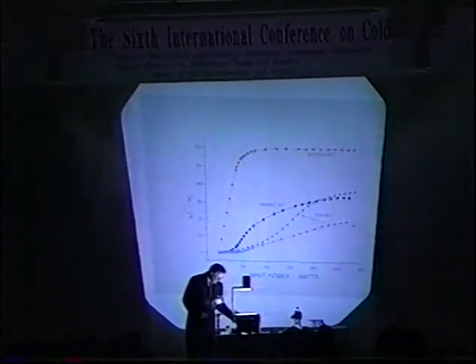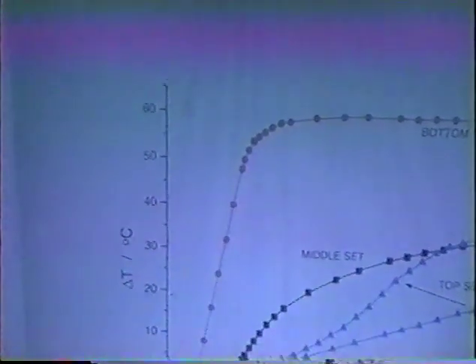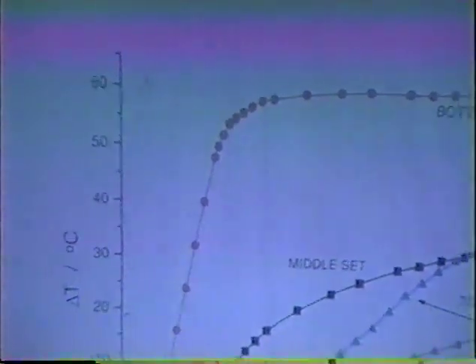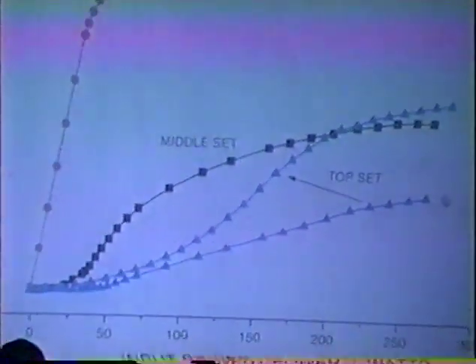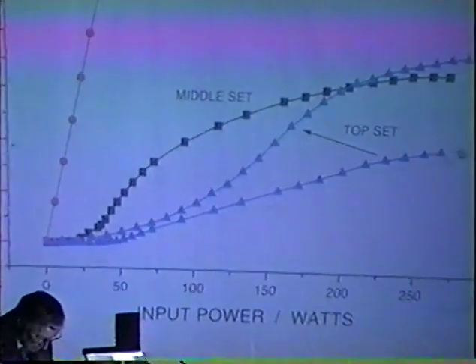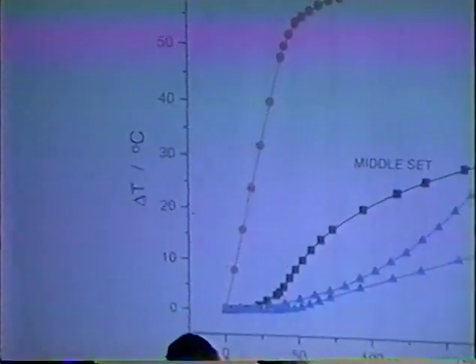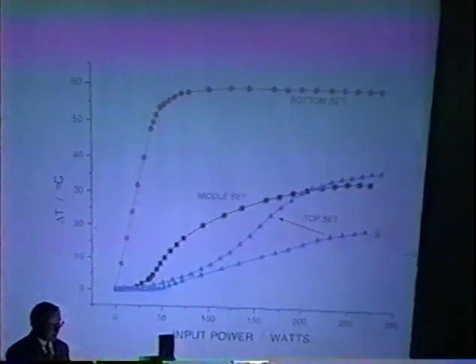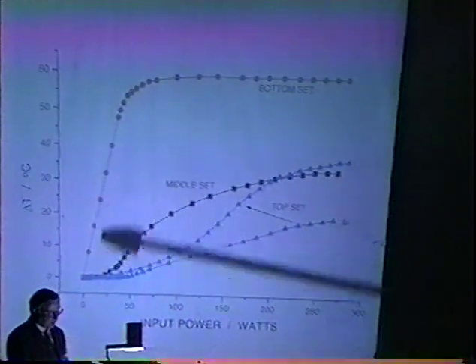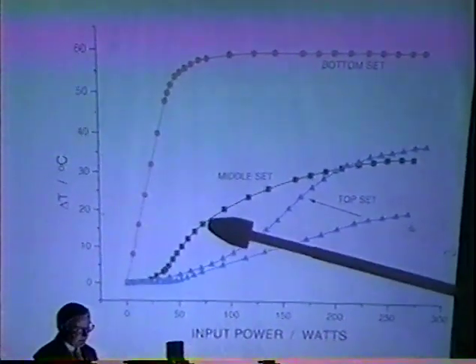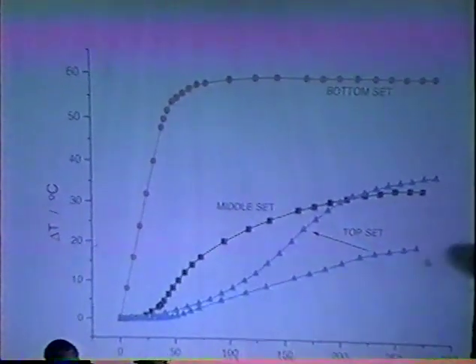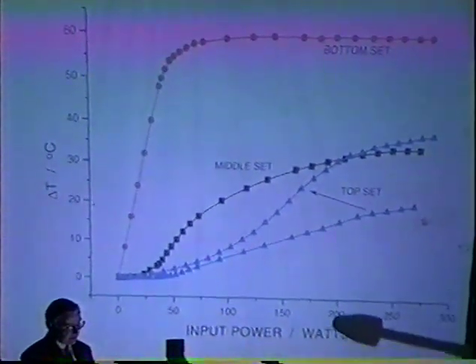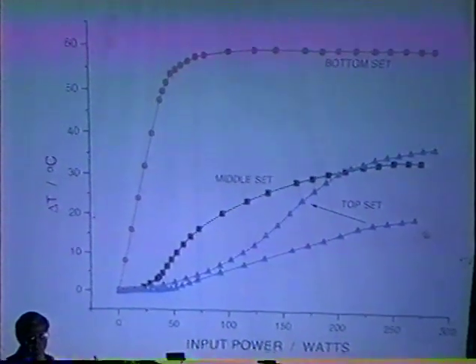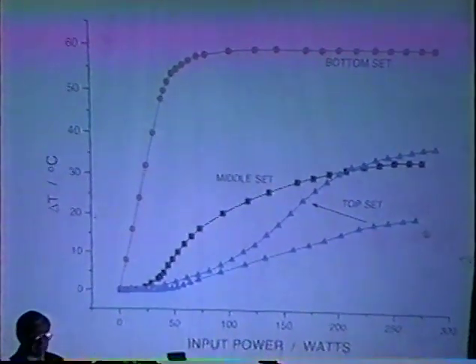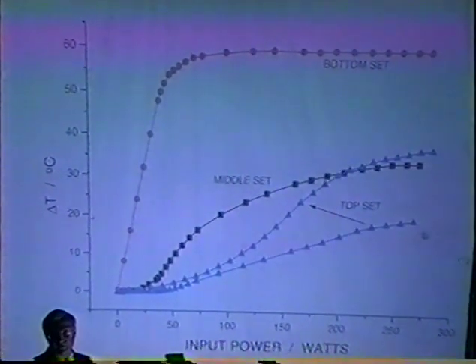One important point that should be made is that the cell then can be modified. As you can see, these calibration curves can have various levels of sensitivity. This is very good for low powers. This one is better for medium powers, and this is better for the higher powers. It may be, though, depending on the final input power, the point at which the cell is boiling, or the operating temperature you want, that you want to shift the sensitivity of these curves.